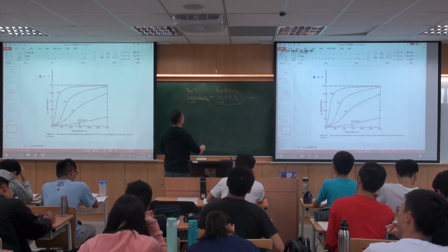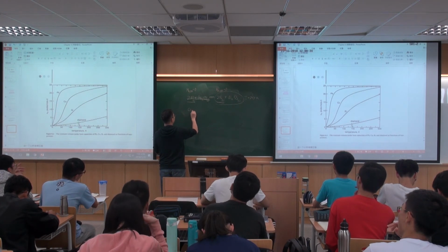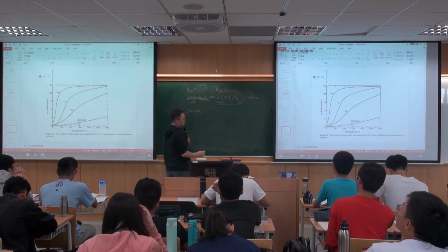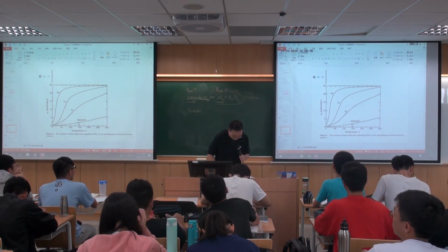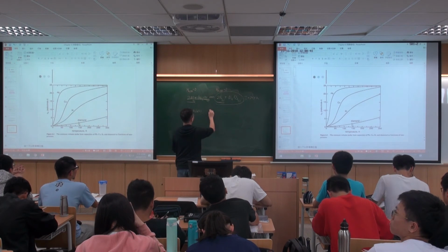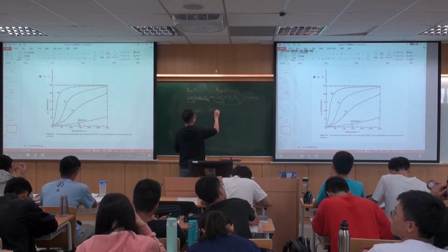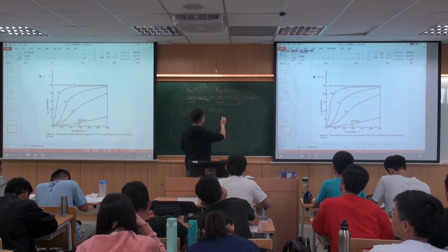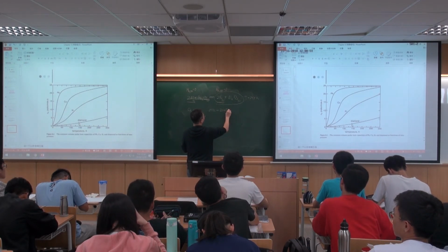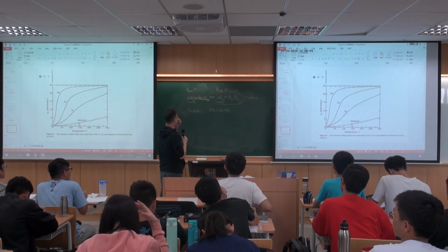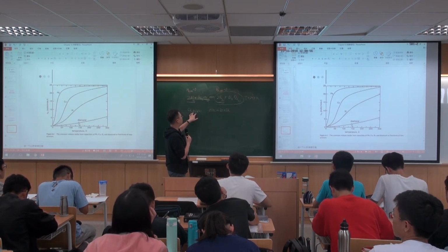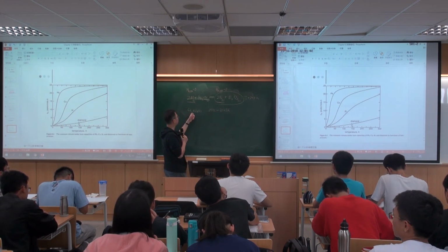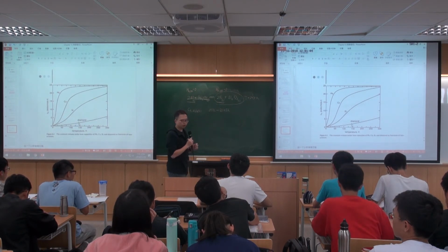So basically, the information that you need is, first of all, CP of aluminum oxide for solid. So this is already given, and the range is 298 Kelvin to the melting point, which is 2325 Kelvin. Okay, so it means that aluminum oxide will be solid until this temperature.